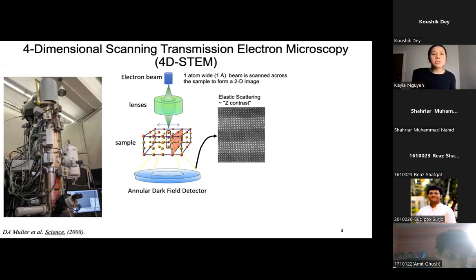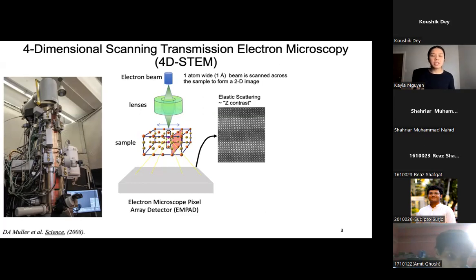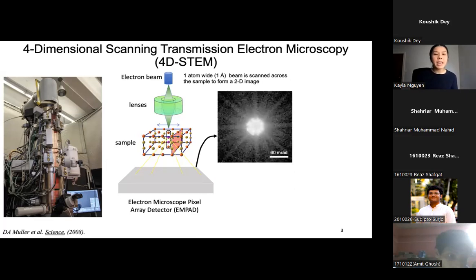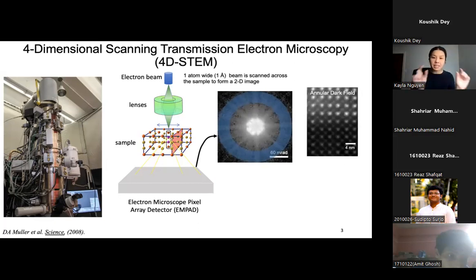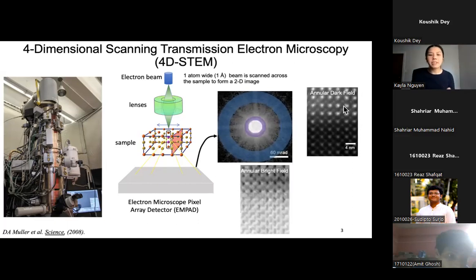One of the ways we can do it is utilize a technique called 4-dimensional scanning transmission electron microscopy, 4D STEM for short. Now, instead of having an annular dark field detector that collects scattered electrons and integrates them up to get these really nice atomic resolution images, we can replace that with a direct electron detector, in this case the electron microscope pixel array detector, EMPAD. For each scan position of the electron beam, we're collecting the full electron diffraction pattern. Now we can make virtual masks, for example, the same size as an annular dark field detector, and reconstruct our annular dark field image, or we can choose different regions of the diffraction pattern where we can integrate that signal up, for example, to reconstruct an annular bright field image.